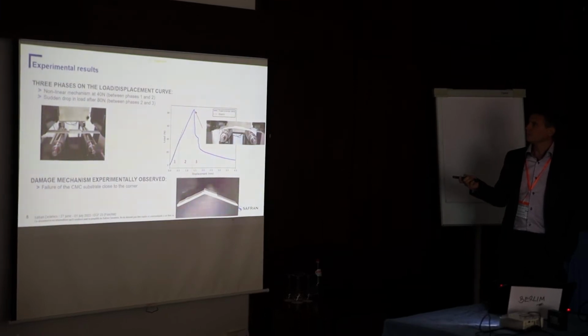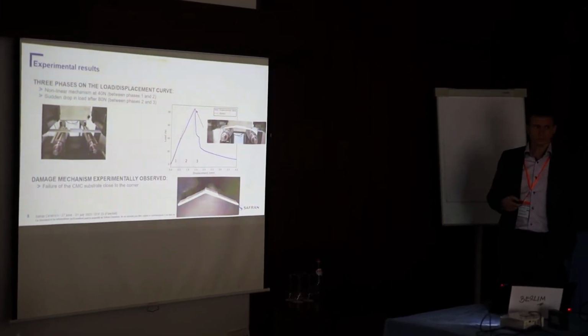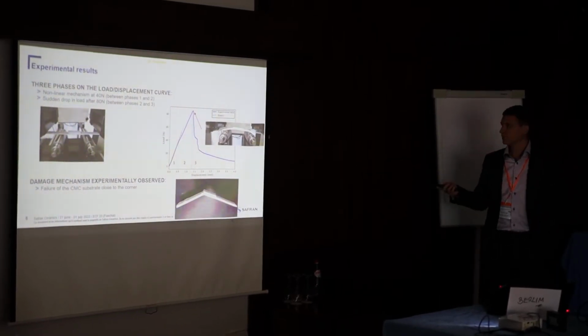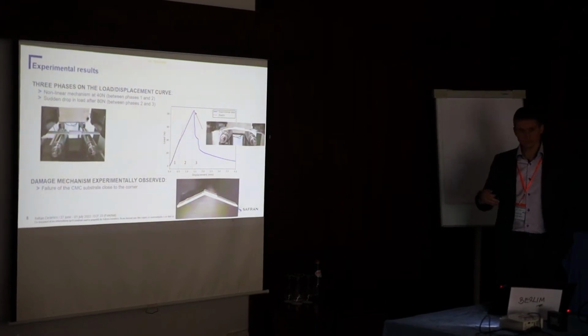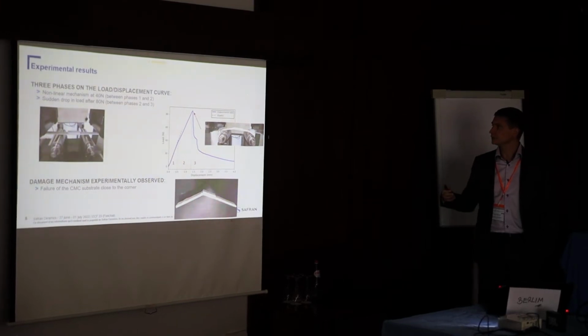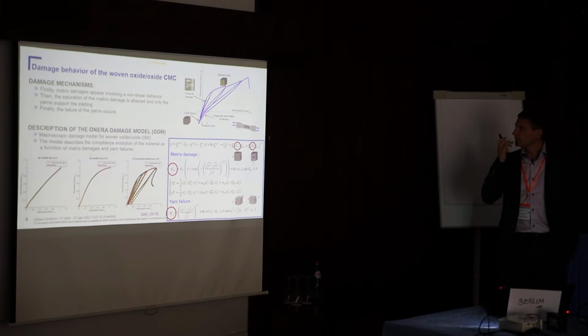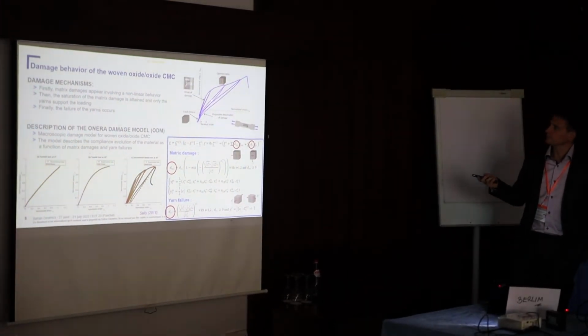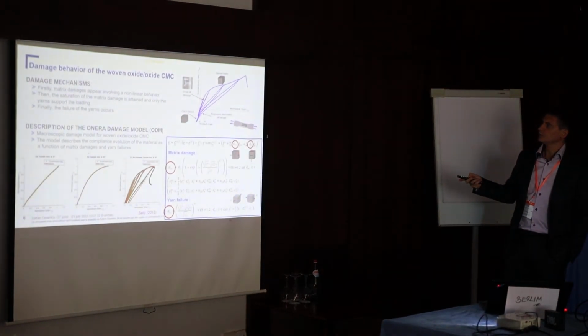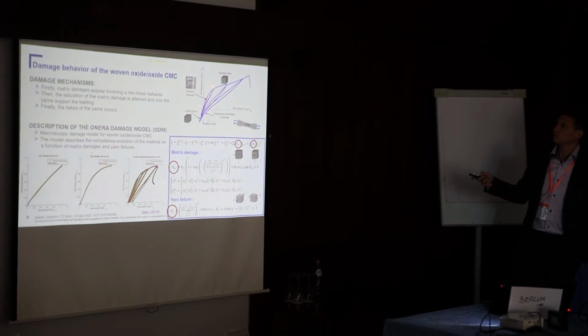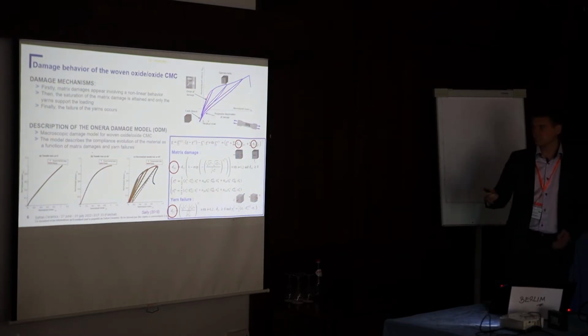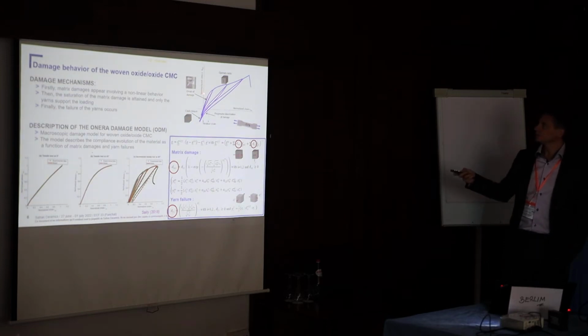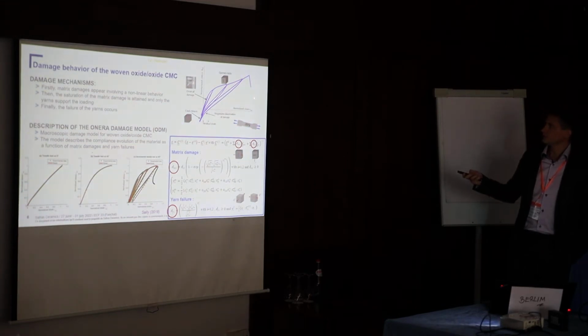But if we use an elastic model, we can't understand why we have the first nonlinearity. So we have to introduce damage mechanisms of the CMC substrate, and this is what we have done. Here we have the classical damage behavior of CMC materials under tensile test. Firstly we have elastic behavior, and then matrix damages appear, which involve a nonlinear behavior. Under tensile load, we have matrix damage, and then a saturation of this kind of damage, and only the yarns support the loading until they fail.